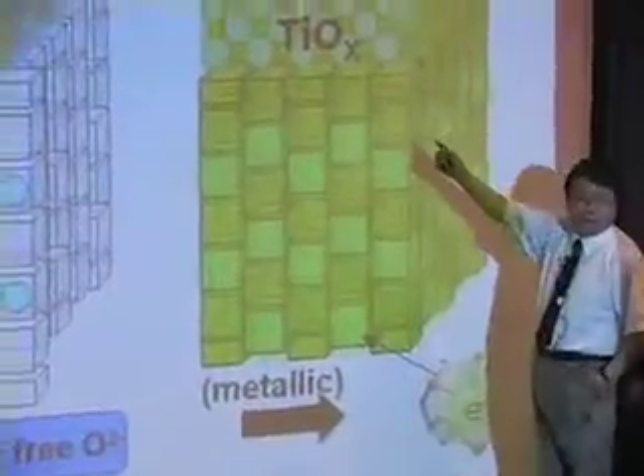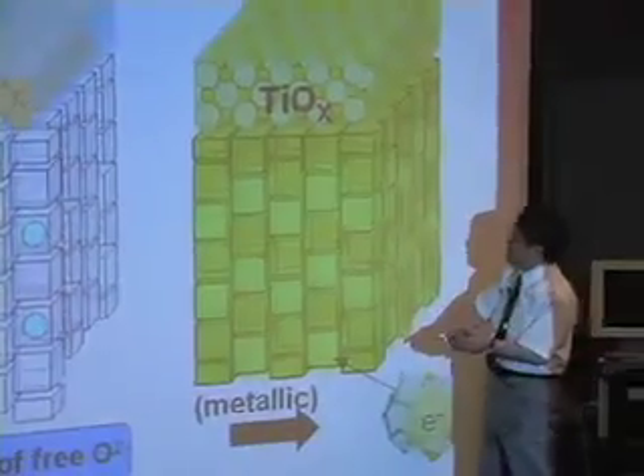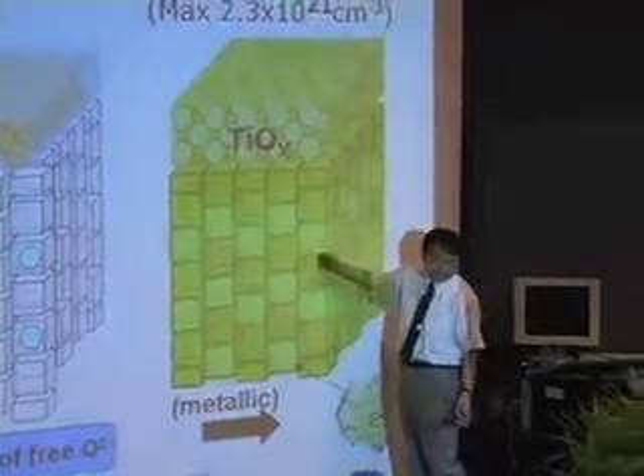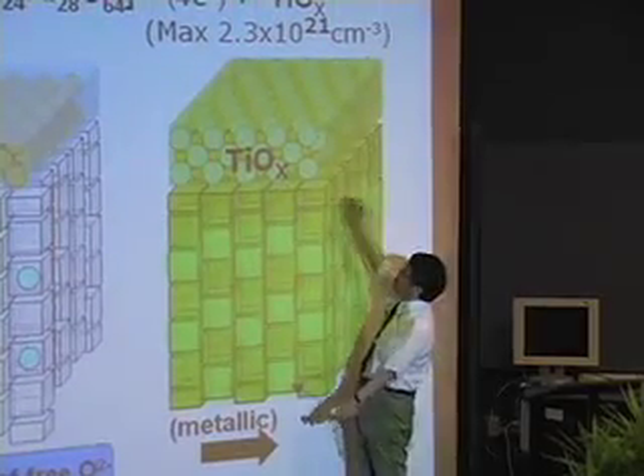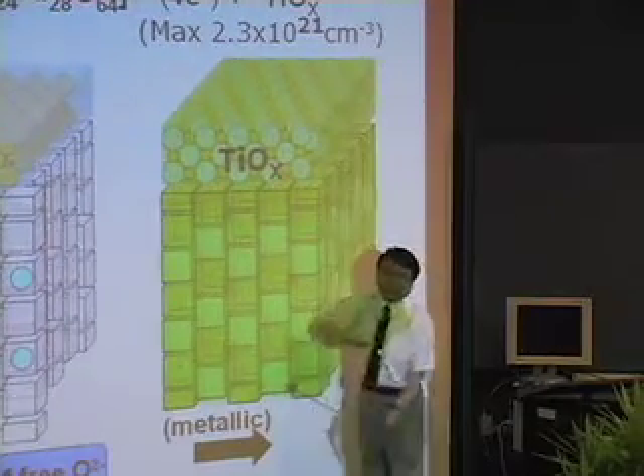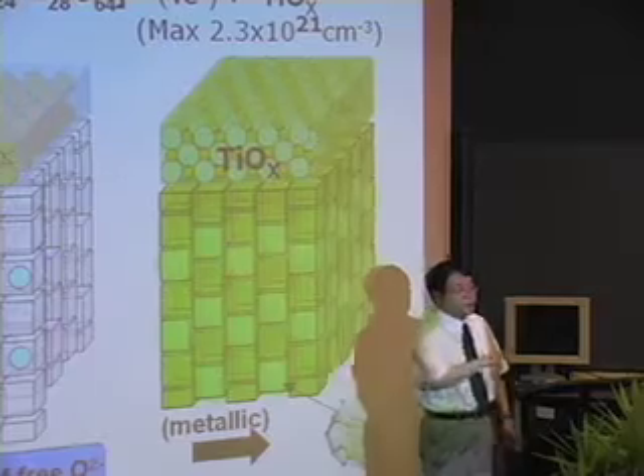So the titanium suboxide is formed on the surface. As a consequence, an electron is injected. After that, the surface titanium oxide layer is removed by mechanical polishing.